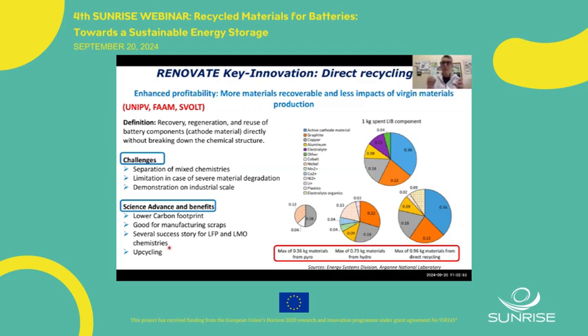So we can directly heal the cathode by adjusting the regeneration, the morphology, for example, the lithium stoichiometry, because we have parasitic lithium loss. And this really fits the LFP-based chemistry, which is now considered a low-value chemistry. So it's really hard to justify a hydrometallurgic or also pyrometallurgic approach when we want to recover just lithium iron phosphate.